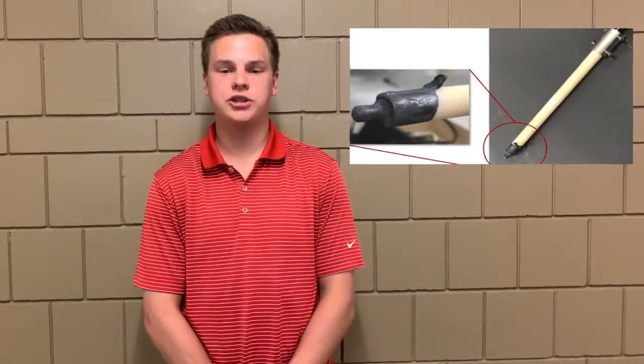The fifth phase was our first industrial experiment. During this experiment, we tested the jacket assembly in a small crucible with molten steel, similar to that of our company's environment. This test gave us mixed results. We saw that the sapphire fiber performed as expected, but the jacket assembly experienced thermal shock and cracked as a result.